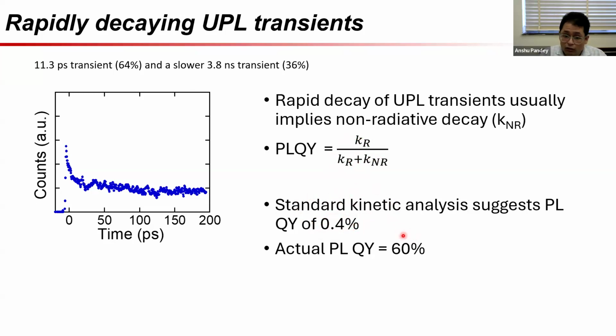In fact, that is wrong, because the actual PL quantum yield of this sample, as measured very carefully, is around 60%, slightly in excess of that. And there are other samples we measured over the course of time with quantum yields even larger, approaching 90%. And yet this dynamic seems to stay and stand out. So what is the surprising thing happening over here? It clearly is not a non-radiative decay channel.